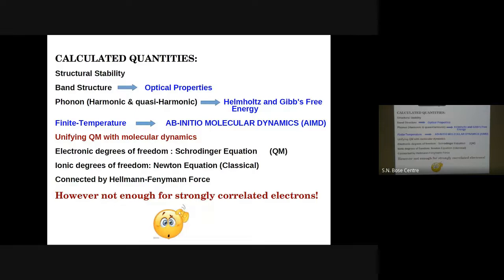So far all were 0 Kelvin calculations, but you can also do finite temperature calculations through ab initio molecular dynamics, which basically unifies quantum mechanics with classical molecular dynamics by treating the electronic degrees of freedom by solving the Schrodinger or the Kohn-Sham equation, which is fully quantum mechanical in description, while the ionic degrees of freedom, which are much heavier compared to electrons, are treated classically by solving the Newton equation, and these two are connected by the Hellmann-Feynman force, because the force acting on the ions is calculated in a fully quantum mechanical way by solving the electron problem. However, this is not enough for strongly correlated electrons, and that's where all this business of modeling comes in.